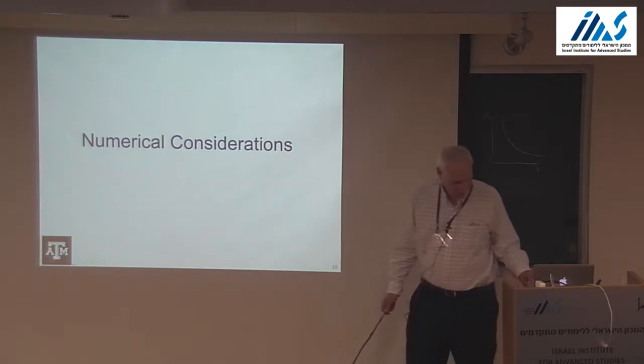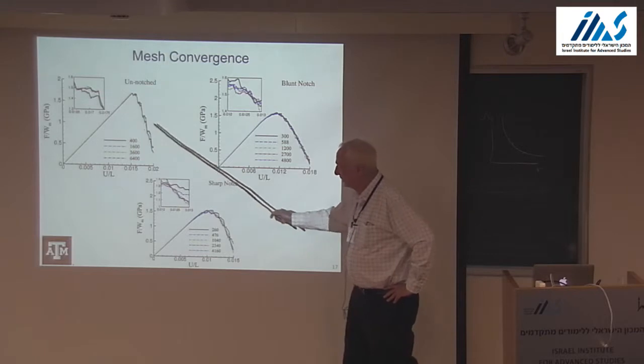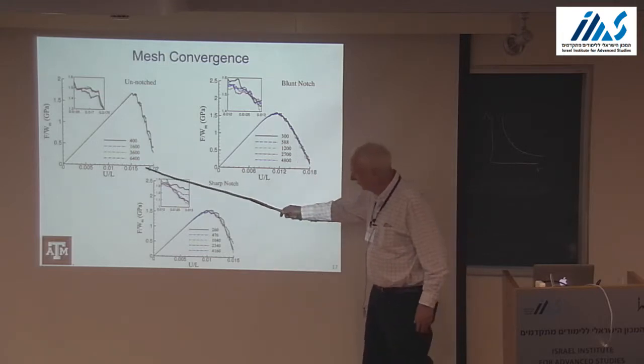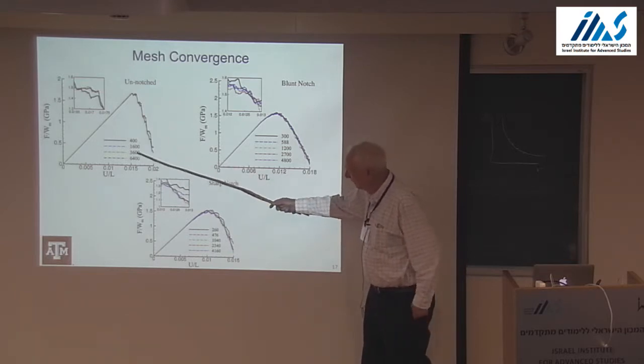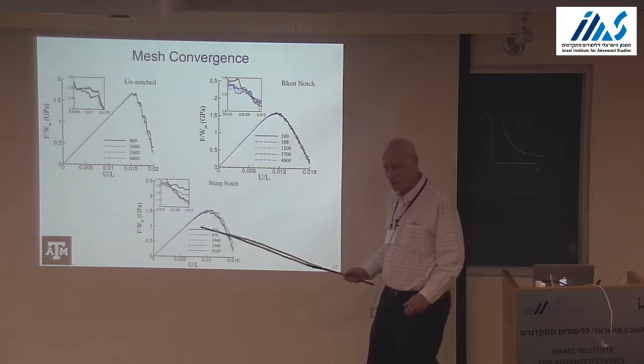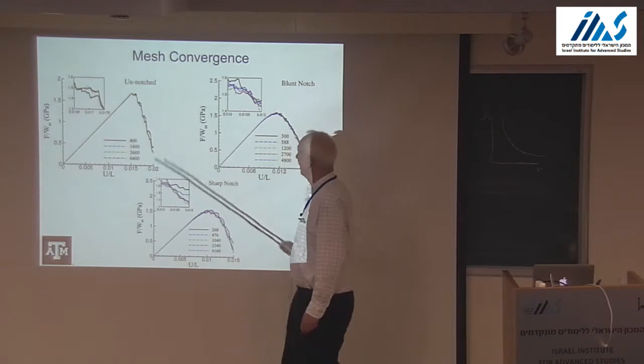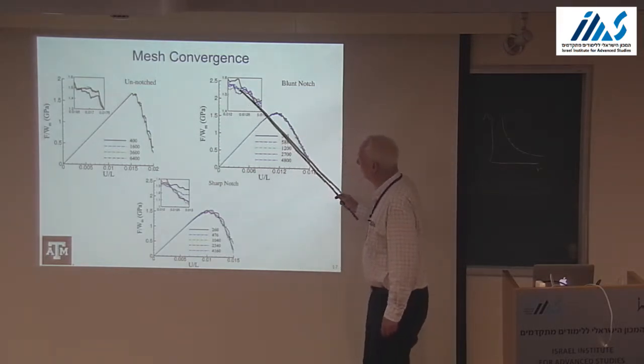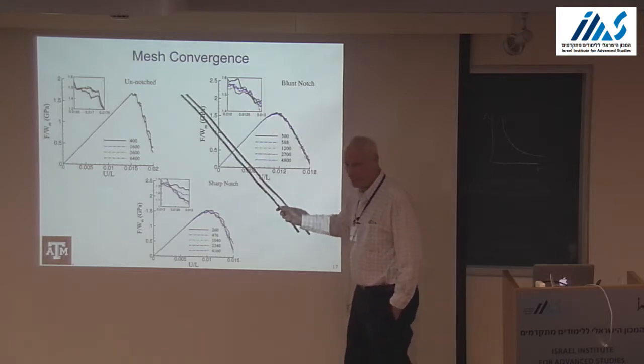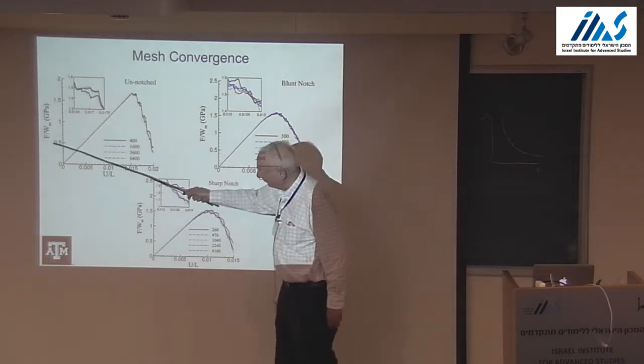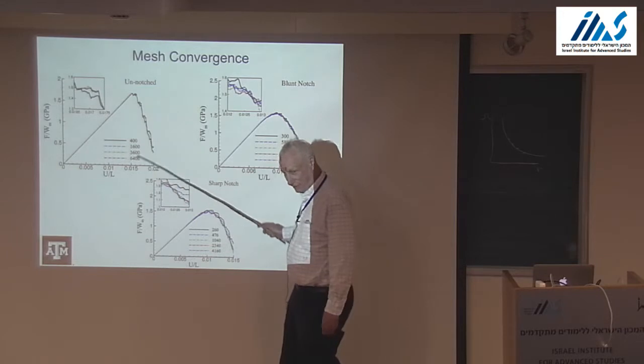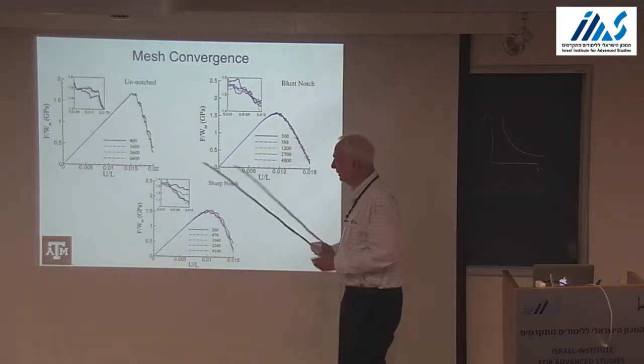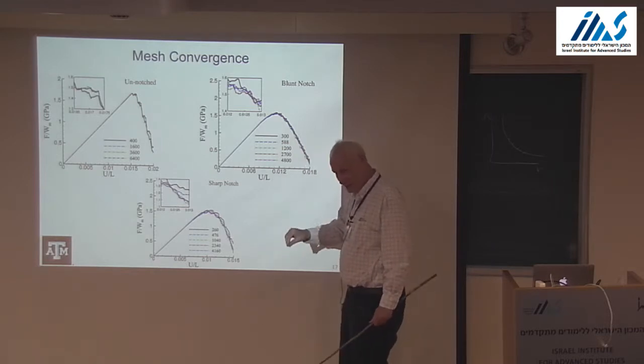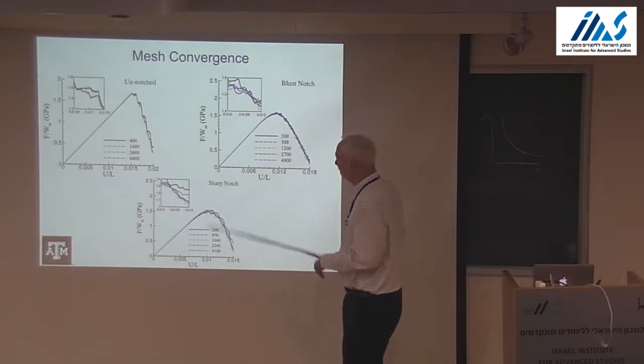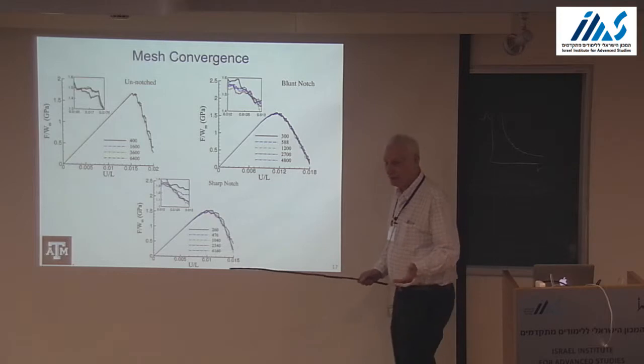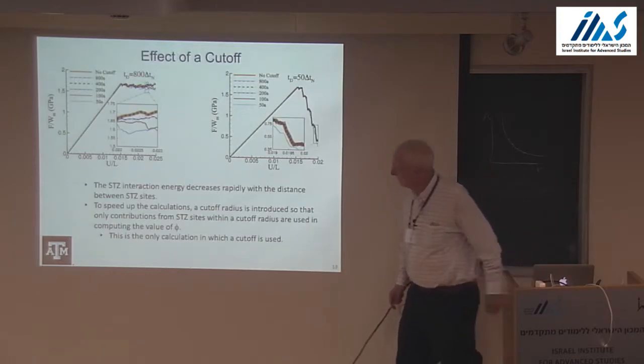Okay, so we do numerics. What are the numerical considerations? One is we wanted to check on convergence. So we looked at different meshes, and if you get beyond about 1600, things fall essentially on top of each other. You can see here in the cutout, the curves begin to fall on top of each other. The overall stress, the force divided by the width versus the imposed strain. One thing you'll notice, and I'll get into more detail, is these stress drops, bursts, associated with bursts of activation. It depends on the notch acuity. Different notches have different burst frequencies.